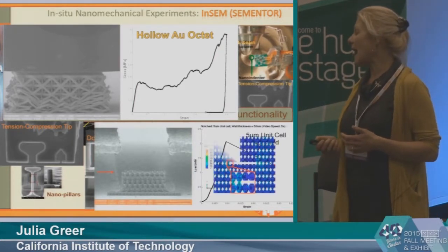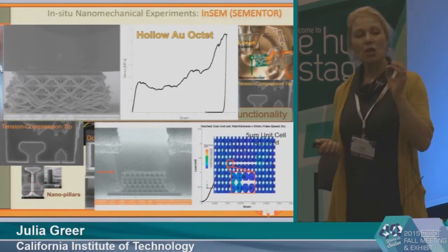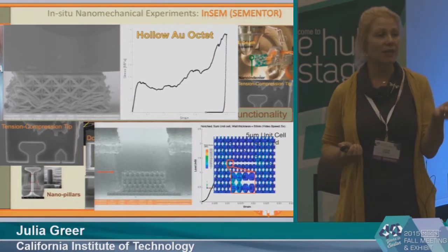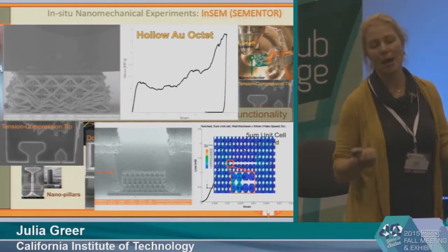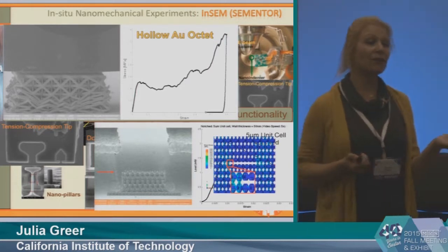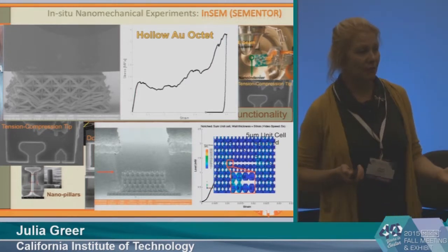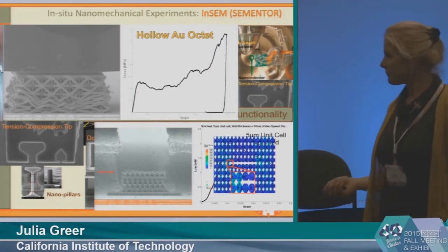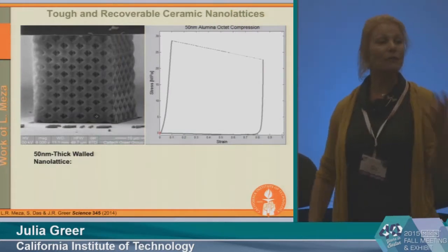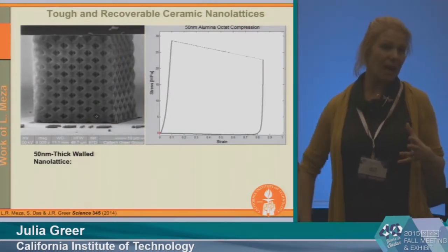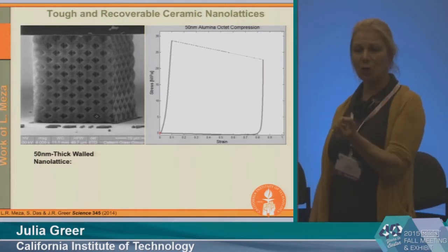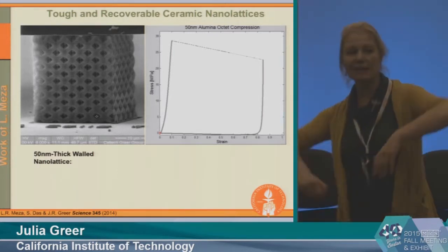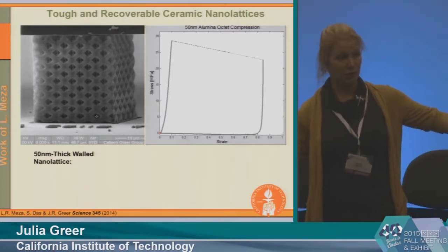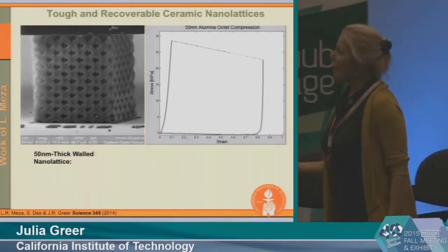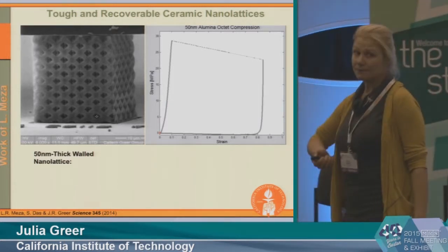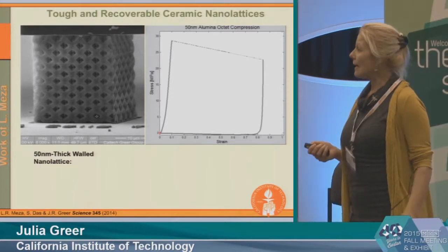And what's nice is that after we fabricate these, we can also model them very precisely with exactly the same geometry and try to use perhaps continuum models or other kinds of models to understand their deformation and failure behavior. So now that I told you a little bit about how we make them and how we conduct our experiments, the big question still remains: can we observe the nanometer size effects in something that's much larger than a single nanostructure? So this is an octet hollow alumina nanolattice, and the wall thickness here is about 50 nanometers.